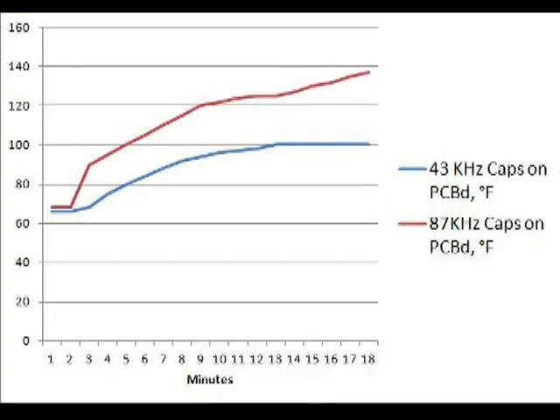The onboard capacitors definitely got hotter at 87 kilohertz than they did at 43 kilohertz. Of course, I didn't have the extra capacitors for the 87 kilohertz test, so we can't look at them. Note that the temperature had not stabilized at the end of the 87 kilohertz run like it did at the end of the 43 kilohertz test.